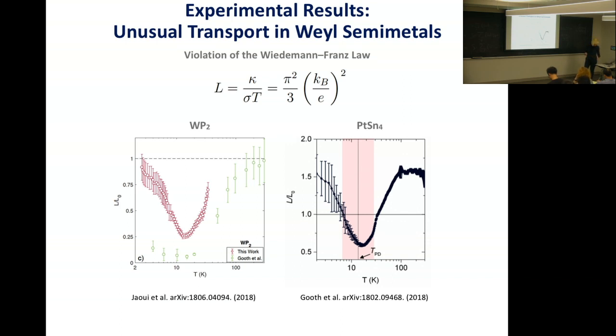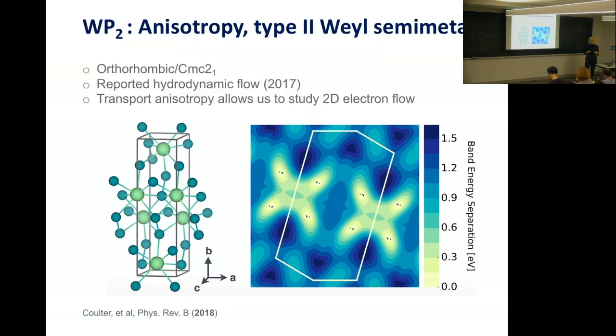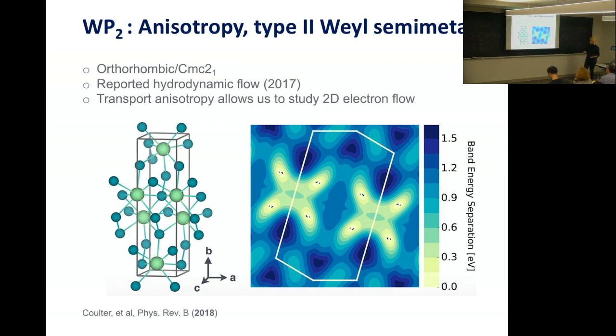One way to think about this is to calculate everything about the material, in particular the scattering properties. We should see a separation of timescales — the electron-electron times should be very different from the electron-phonon scattering times. That would allow us to establish whether the electron hydrodynamics is truly electron hydrodynamics, and if the phonons are carrying more energy than expected, that should show up in a temperature-dependent scattering rate. I chose tungsten phosphide: it's low symmetry but has a single plane for transport, so it can look quasi-2D. It's a type-2 Weyl semimetal, and the full scattering matrix lets us diagnose the contribution of the Weyl points to transport.